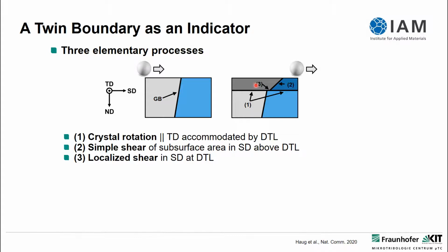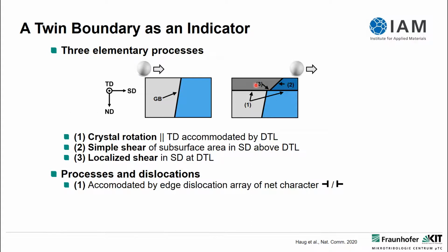What elementary processes in the material might be behind that? The first one, the formation of the dislocation trace line and rotation around an axis perpendicular to the screen, might be accommodated by edge dislocations which have a net character like this, or more like this if we have sliding from left to right.